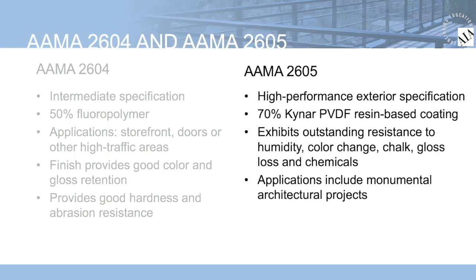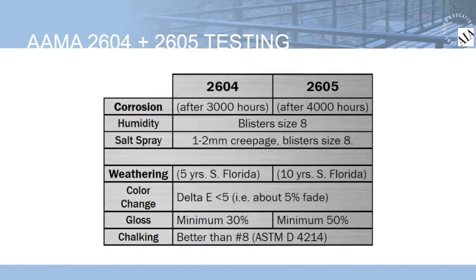are frequently maintained. As part of the testing requirements, the powder coat is tested daily for corrosion resistance and coating adhesion according to industry standard specifications. It is also tested in an accelerated weathering environment for several thousand hours to test weathering quality. After 5 years, or 10 for AAMA 2605, of outdoor installation in conditions like southern Florida, the powder-coated product should have almost no color change and exhibit very little chalking. Periodic cleaning with a mild soap and water will enhance it and help to protect it from harmful agents.